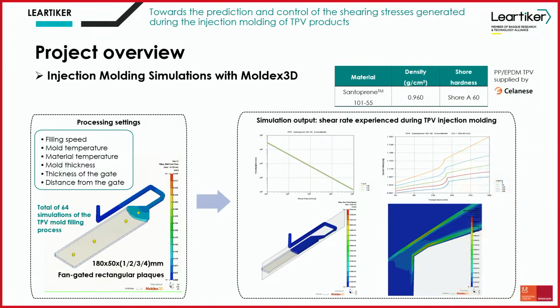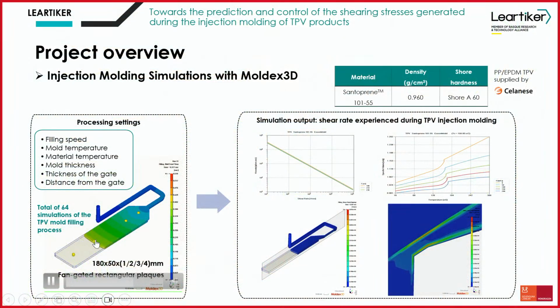Why? Because the redesign of a component, so shifting from rubber to TPEs, has other challenges, for example, related with the wall thickness, because in this case we are injection molding, so usually we need wall thickness less than 4 millimeters to avoid warpage, to avoid void generation, and also we want to locally analyze the effect of the injection molding on the shear rate, so that's why we also analyzed the distance from the gate, so we analyzed the generation of the shear rates in different positions of the plate.